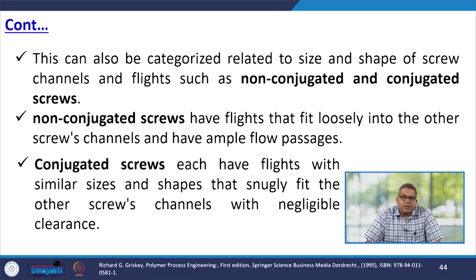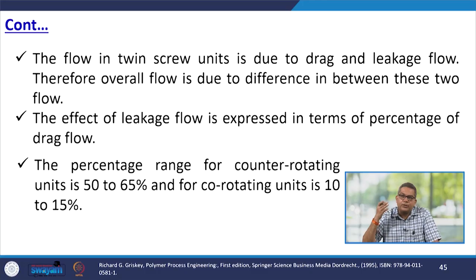Now, conjugated screws each have flights with a similar size and shape and snugly fit into the other screw's channel with negligible clearance. So they become more tight in nature. The flow in the twin screw unit is due to drag and leakage flow. Therefore, the overall flow is due to the difference between these two flows. The effect of leakage flow is expressed in terms of a percentage of drag flow. The percentage range for a counter-rotating unit is 50 to 65%, and for a co-rotating unit is 10 to 15%.